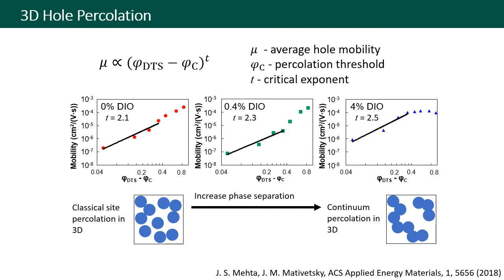Further evidence for a role played by lateral charge transport pathways was provided by percolation analysis of the average hole mobility as a function of active layer composition. We fit the data near the percolation threshold — in other words in the composition range where charge can barely flow — to find the critical exponent that varies with the dimensionality of the system. This analysis shows that the percolation process in bulk heterojunctions is fundamentally three-dimensional, and that lateral and vertical pathways are both essential for charge flow.